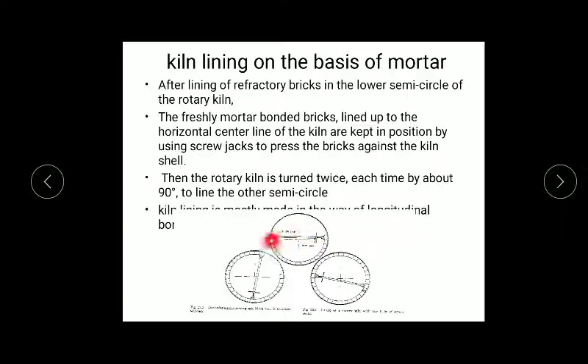Then this screw jack is holding the last 2 refractories, and they are all in compaction. They are all stressed, all compacted, meaning there is pressure from here also and here also, hence they are held tight together, and only these 2 refractories at the end are fixed with screw jacks. Okay, then when this semicircle is completed, the rotary kiln is tilted 90 degrees, and again it is lined here. Then the screw jack is placed here, you can see in this figure. Then after this the rotary kiln is tilted another 90 degrees, and the rest of the refractories are lined here.